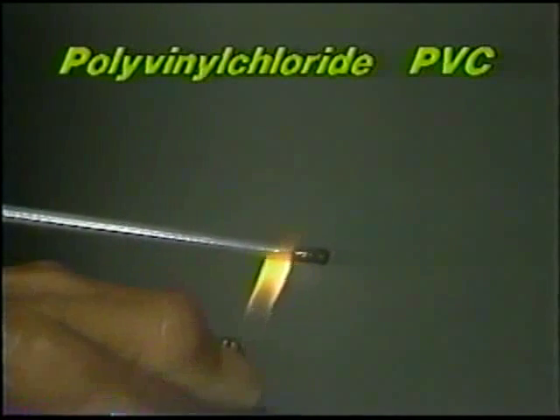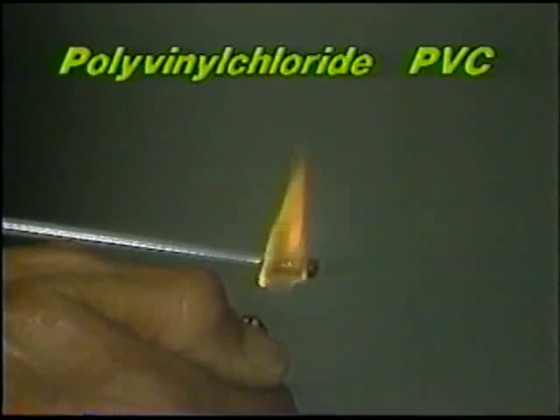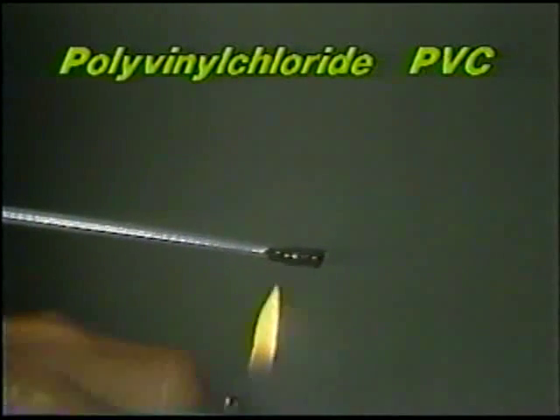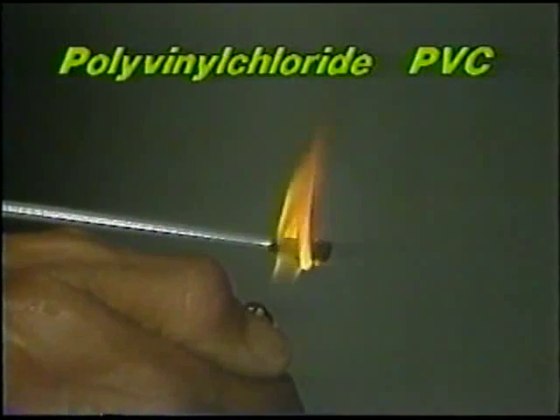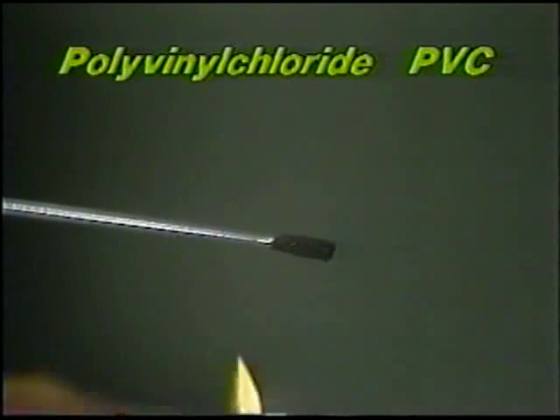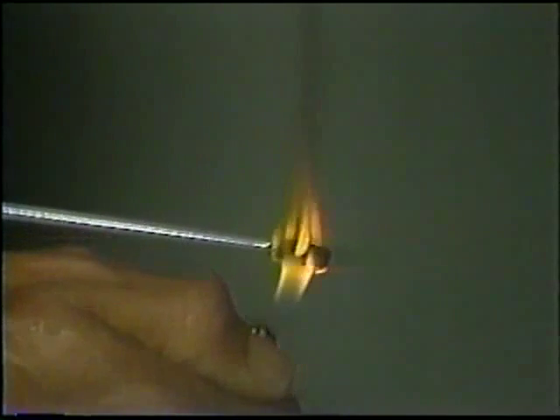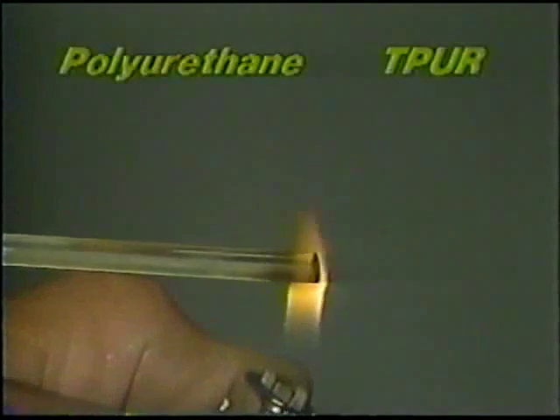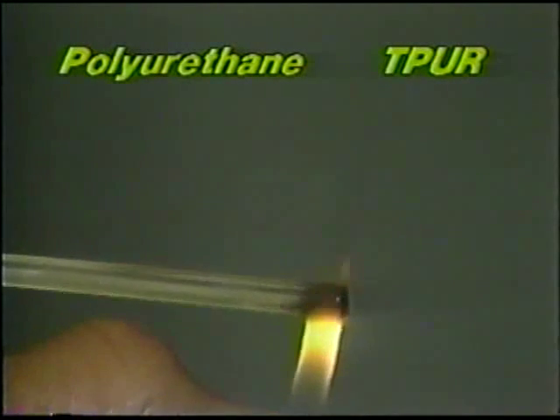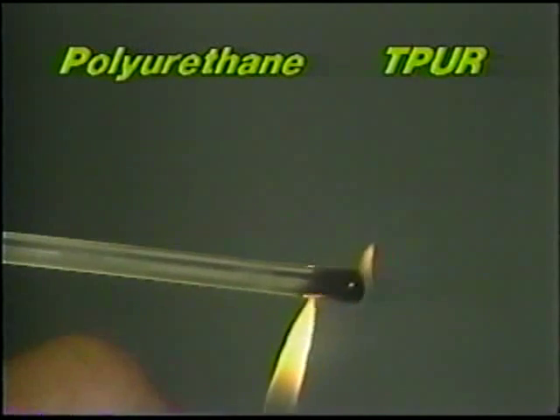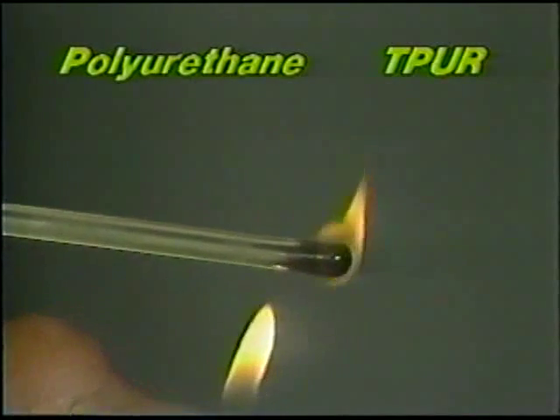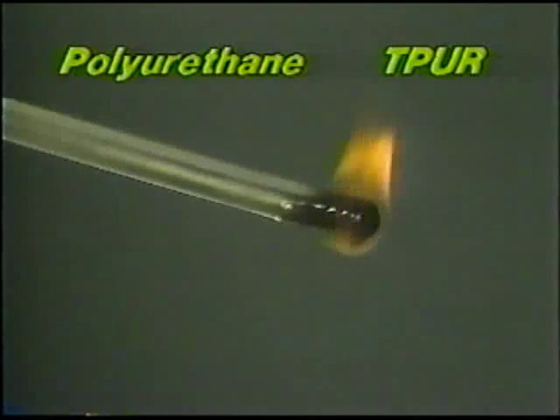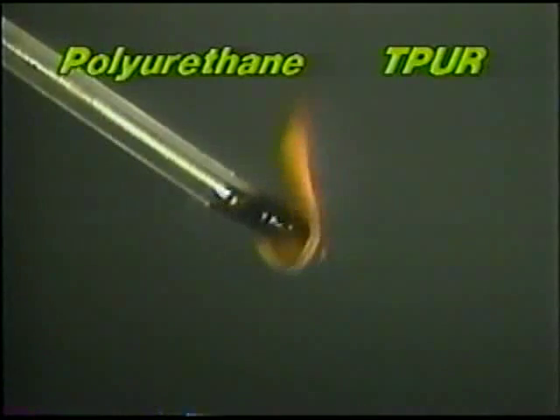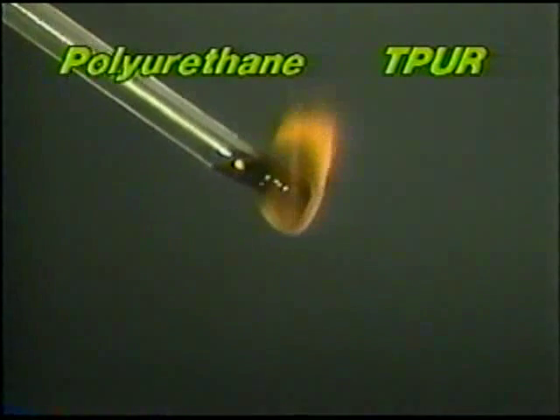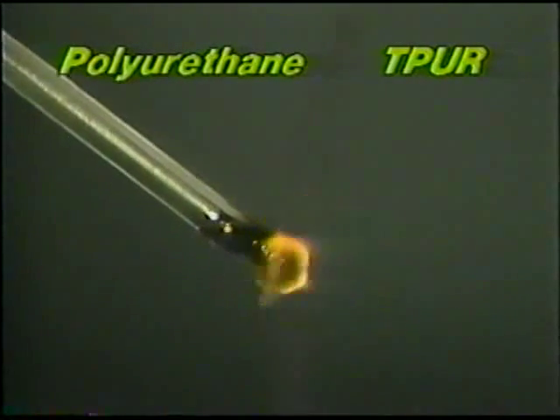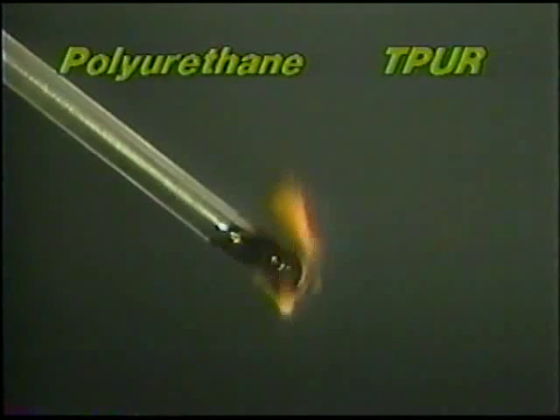Polyvinyl chloride, or PVC, is self-extinguishing. Do not inhale fumes. Polyvinyl chloride will char and give off gray smoke. The 5th kind of plastic you can weld with your Seelye welder is polyurethane, whose code is TPUR. Polyurethane is the most flexible of the 5. It burns with a sputtering yellow-orange flame and gives off black smoke and continues to burn when flame is removed.